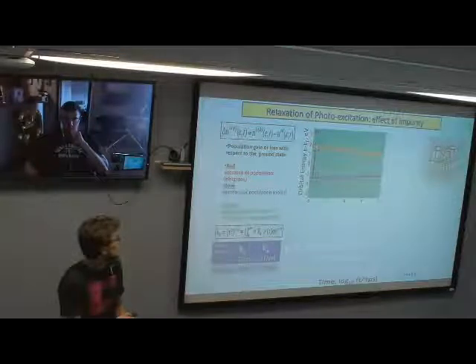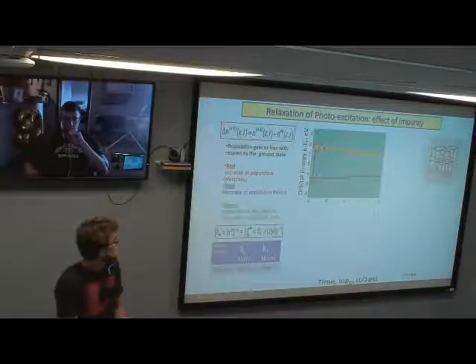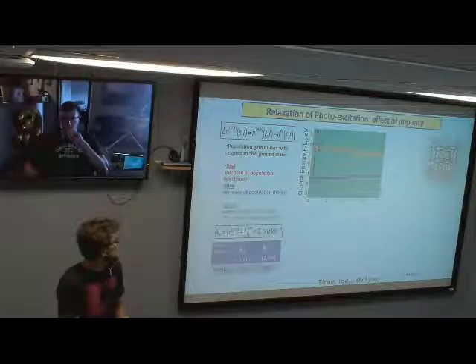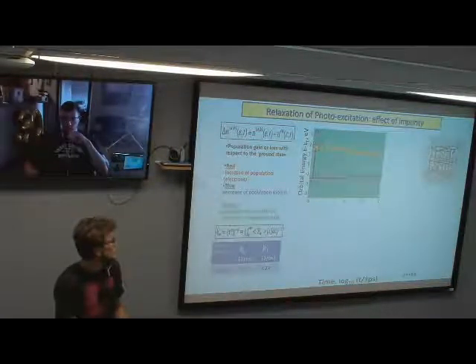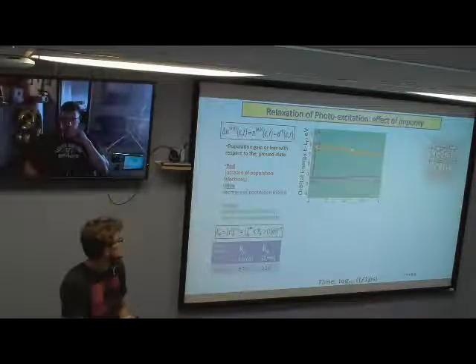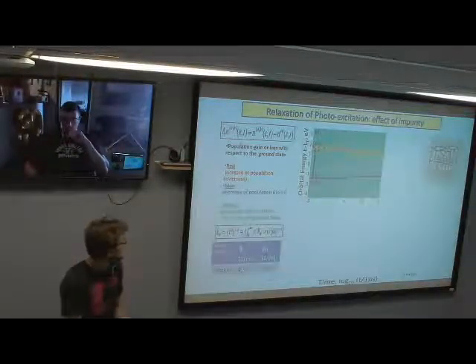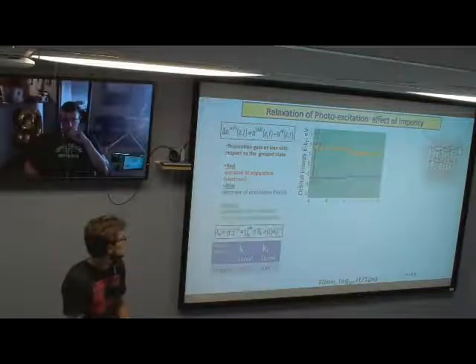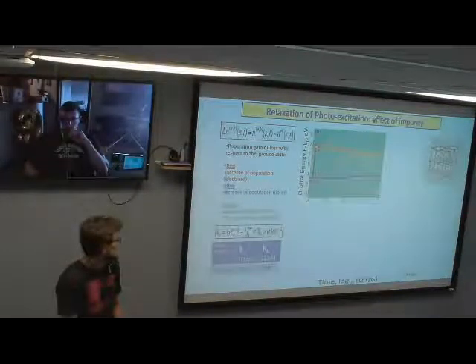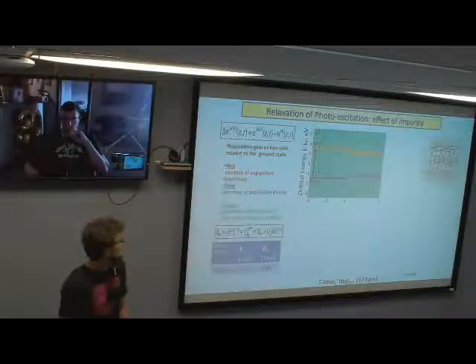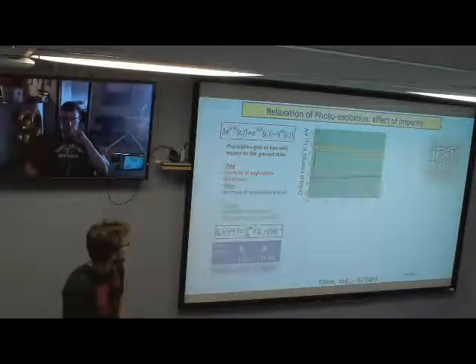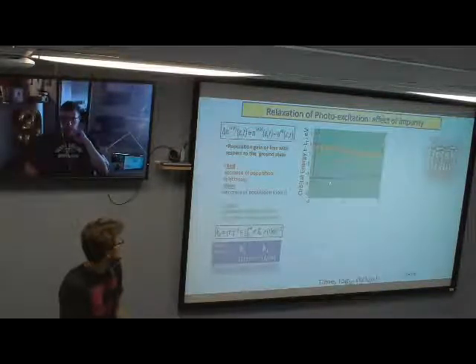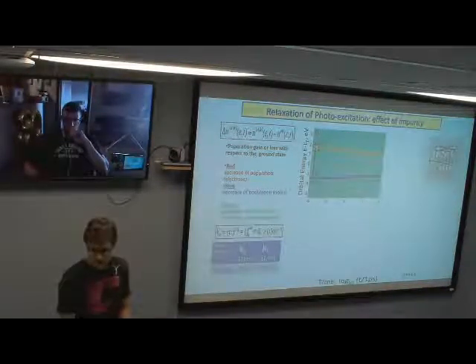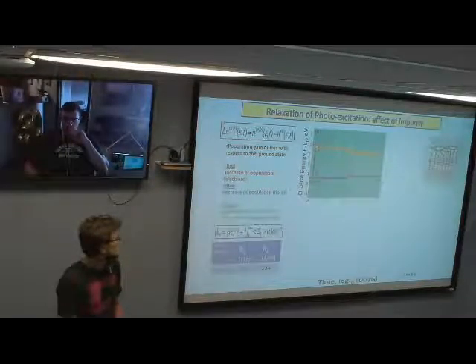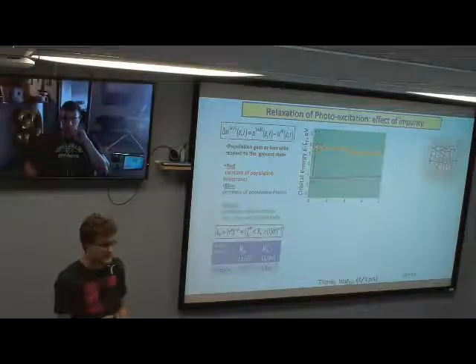The yellow lines represent changes in electron density, or occupations in time, and the blue represent increases in hole density in time. And then the dashed lines just represent energy expectation values. And this is on a log time, so negative 3 would be 1 femtosecond, and then 0 would be 1 picosecond. You can extrapolate the time scale that way. And so for these systems, we see that the hot carrier cooling occurs in the sub-picosecond range, so above 100 femtoseconds, but below 1 picosecond, basically.